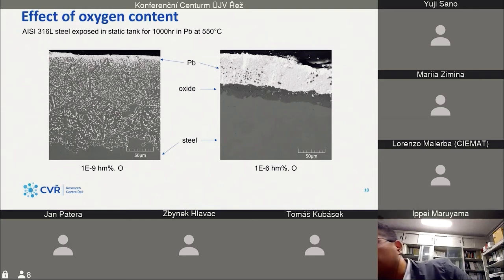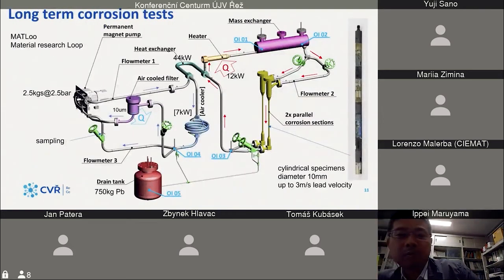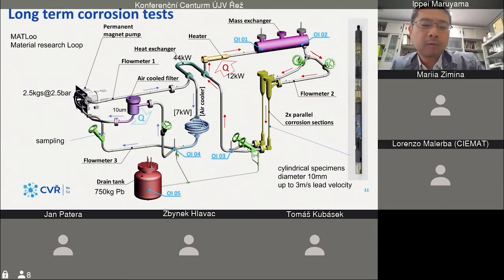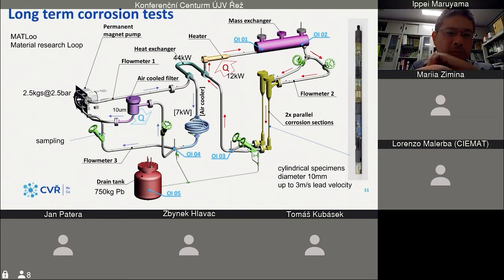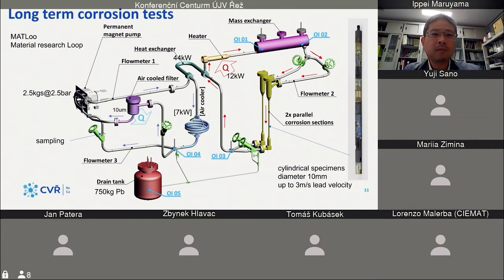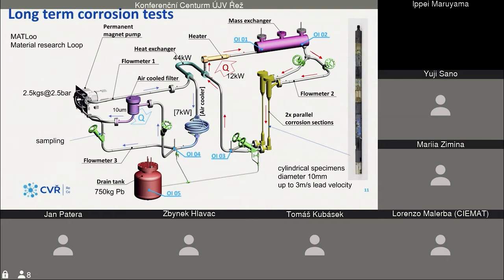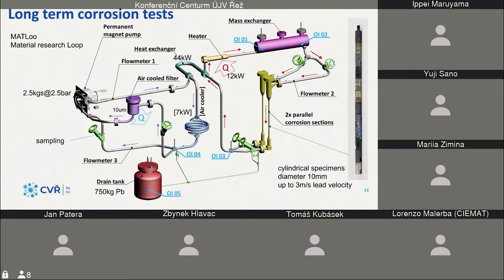Okay, so for some flow tests, we built up a loop. We call it MATLoo, it's the Material Research Loop. It's non-isothermal, so it has a cold leg on the left. There is a pump and filter, and on the right there are two parallel corrosion sections with narrow channels with specimens. There are cylindrical specimens of 10 millimeters diameter, and we can reach 3 meters per second there.